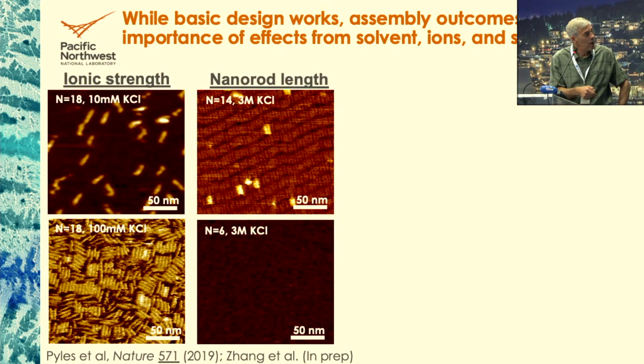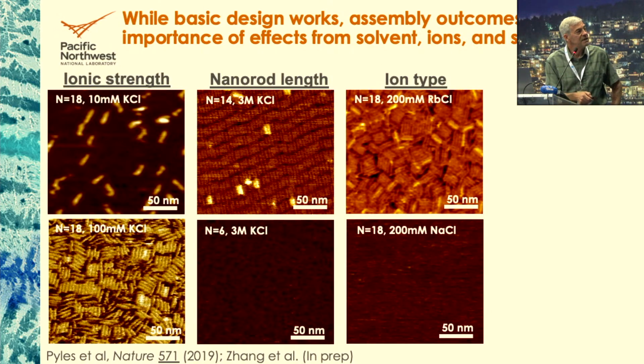If we look at the nanorod length, I showed you we can go to the smectic phase. This is actually a 14, not an 18. But if we go down to n equals 6, you see nothing. It's not because there's no protein on the surface. It's because it never gets out of the liquid state. If we now look at different ion types, rubidium does the same thing as potassium, but sodium at the same concentration again leaves it stuck in the liquid state.